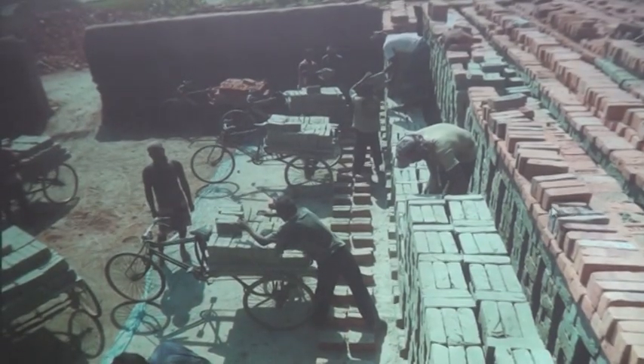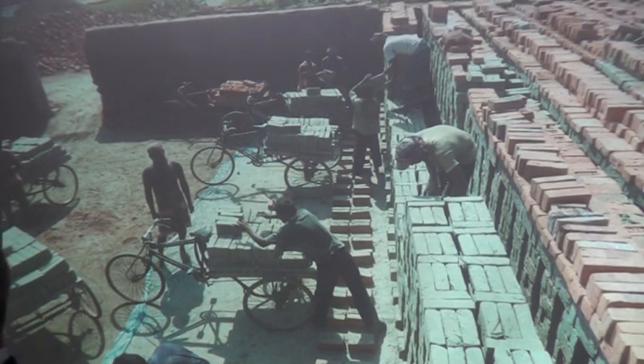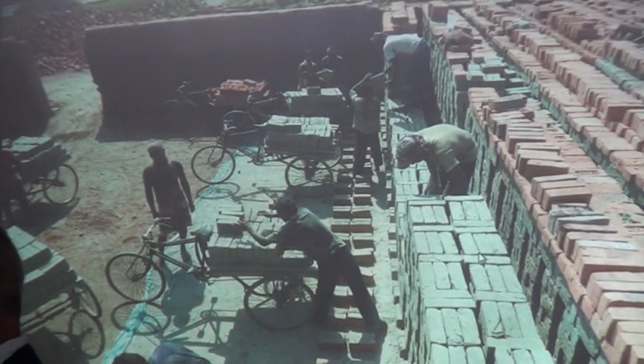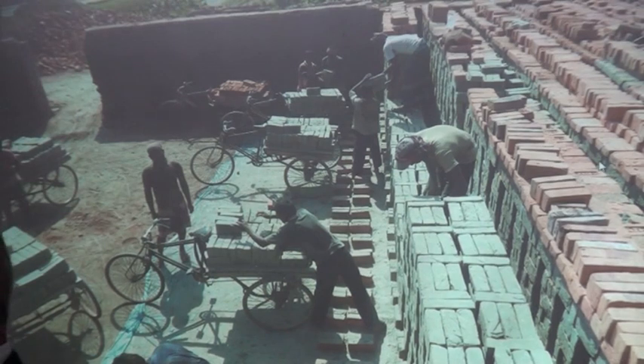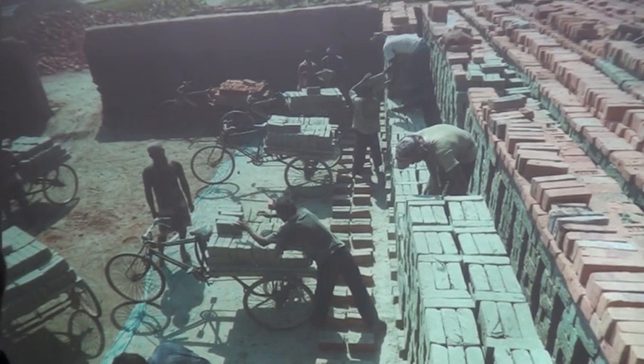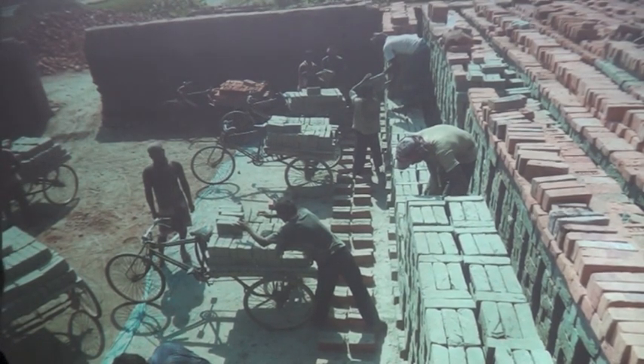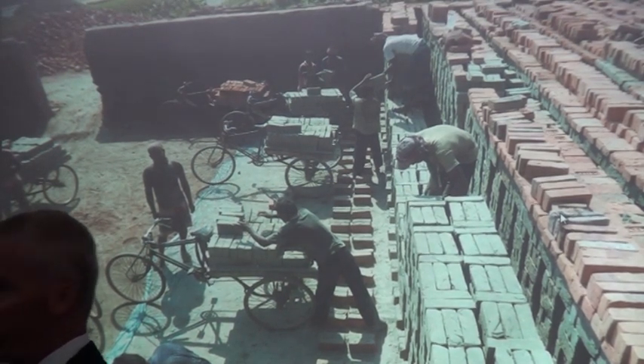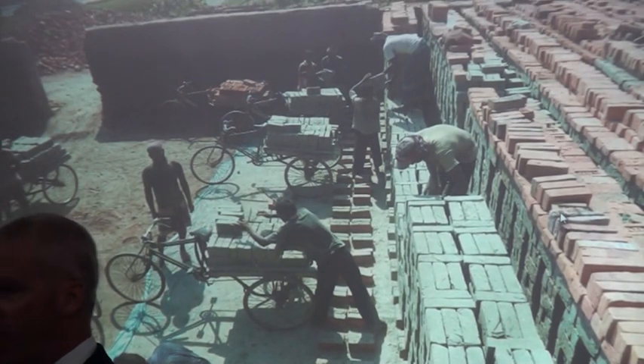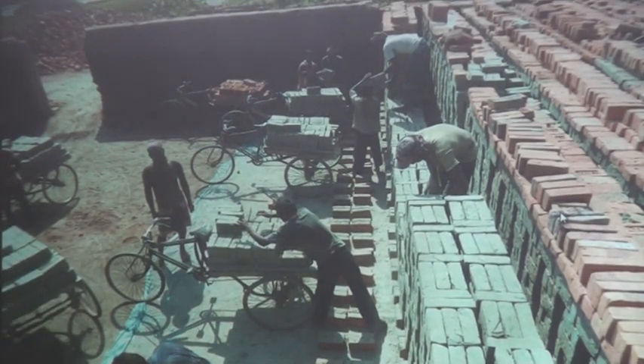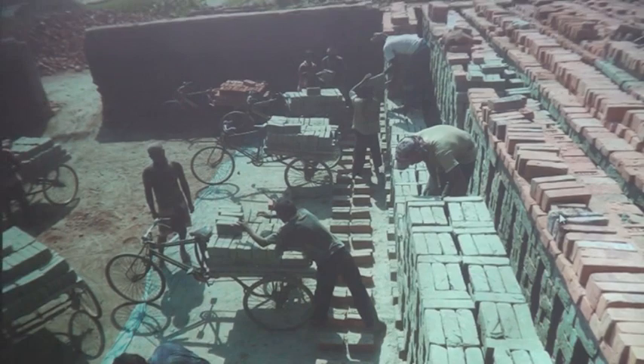It may be noted here, the bricks go in looking very gray. Obviously, a very high iron content in the bricks, which turns the bricks from a gray color to a red color, from the iron in the brick going from possibly a Fe2 state to an Fe3 state, an oxidized iron state, and gives that red color to the bricks.